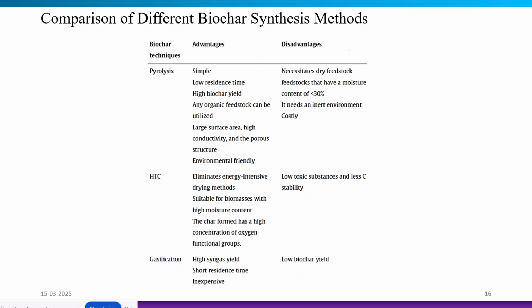We can see the comparison of the biochar synthesis methods. We have discussed the pyrolysis process, hydrothermal carbonization process, and gasification process. In the pyrolysis process, there is low residence time and higher biochar yield. Any kind of organic feedstock can be utilized. We get a larger surface area of the biochar, higher conductivity that we can use as an electrode material, and a porous structure. Obviously it is an environment friendly process, but the main disadvantage of pyrolysis is that the initial moisture content should be less than 30%, and it also needs an inert environment, which sometimes becomes costly.